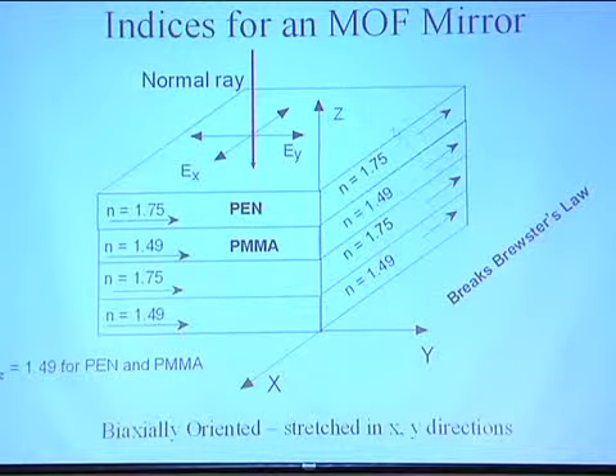This is another cartoon showing a cross-section of the film where we have alternating layers, high refractive index, low refractive index, high refractive, low refractive. And what's unique about birefringent polymers is when you stretch them in this direction, the refractive index goes up in that direction, but it goes down in the thickness direction. So it allows us to make unique mirrors where in the thickness direction, the Z refractive index is matched between these materials. And that allows you to break an old law of physics called Brewster's Law, where the reflectivity stays very high as you go off angle.